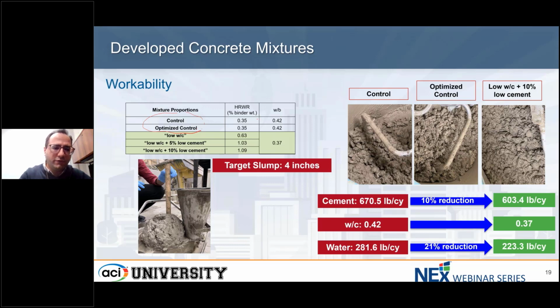So you see, when we move from this control to low water cement ratio, 10% low cement, the high range water reducer admixture content changes from 0.35% of the binder weight to almost 1.1% of the binder weight. This is almost a 3 times increase in the high range water reducer content. Again, the target slump is 4 inch. We want to get to around that 4 inch slump to make sure the concrete is placeable. So these are some examples.